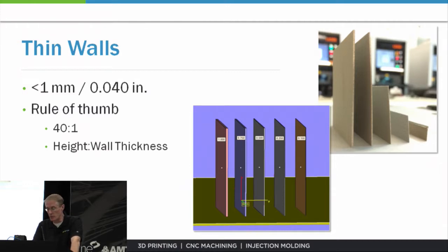And if you look at the one right to the left of it, that's 0.25 mm, about 10/1000ths of an inch. It made it a little bit further, but again, not very far. And you can see it progressively goes on. Now, 0.75 mm, 30/1000ths of an inch, built the whole way, but you can see the warp and the damage in it, right? I would argue we're probably a little bit lucky that one actually completed the build. And so it was the one that was 1 mm, 40/1000ths of an inch, that was able to build successfully without any kind of warping or damage.